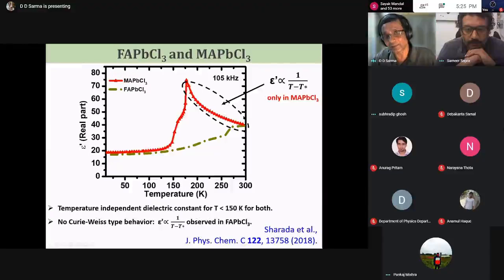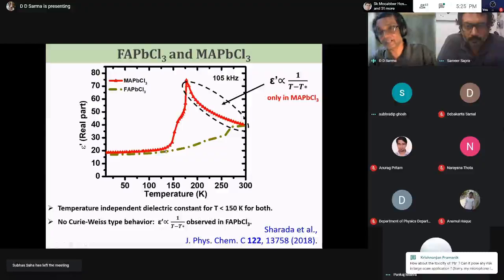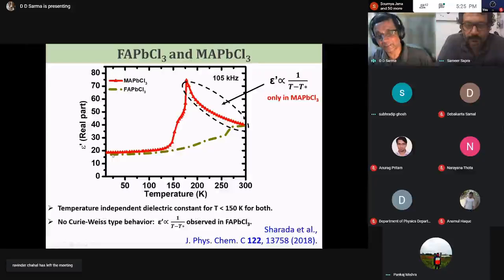And this part is actually because MA is active. You see this very strong deviation in this range. Once you get into the orthorhombic range where the MA gets frozen down and doesn't have this rotation that changes the direction of the MA dipole, you get back the same dielectric constant. Right? Okay.